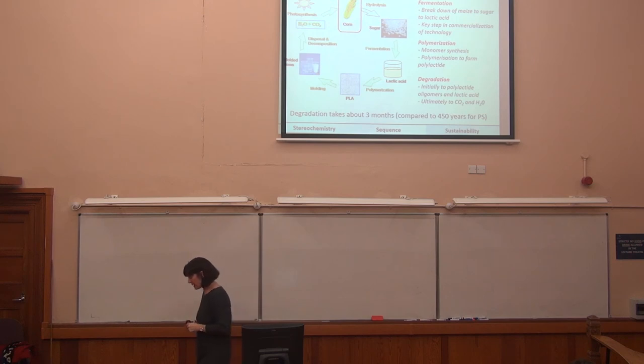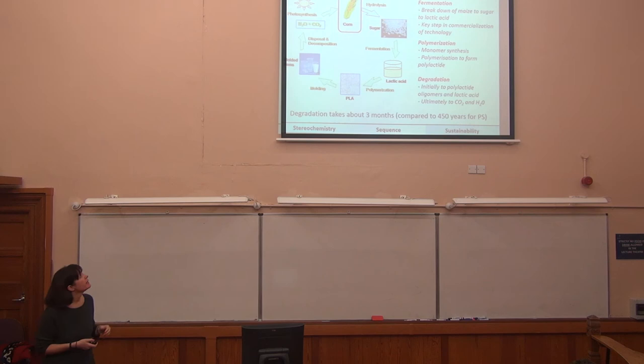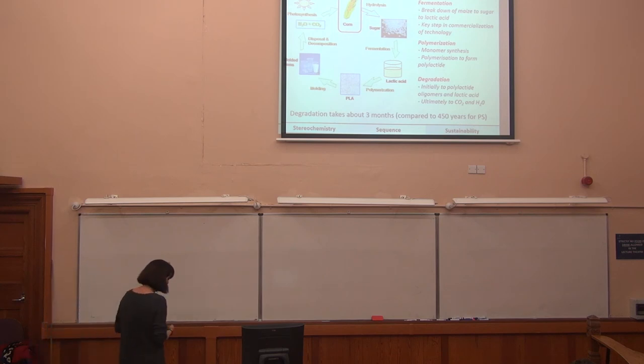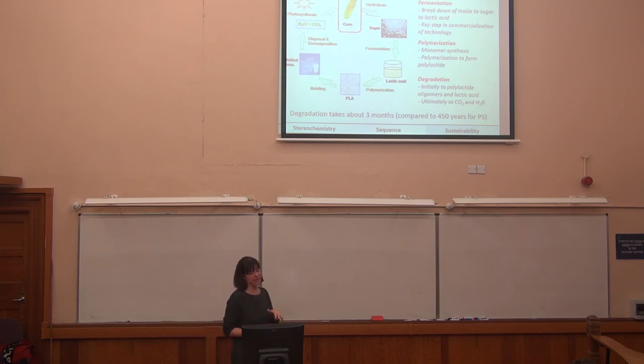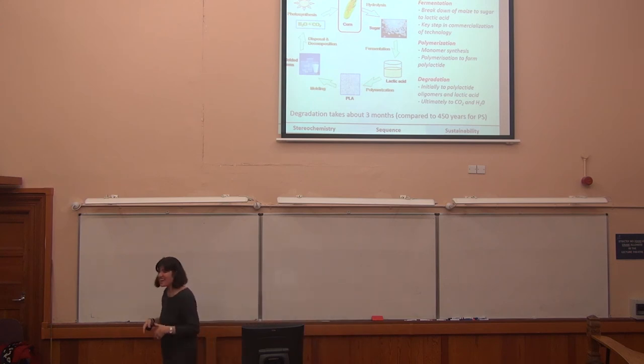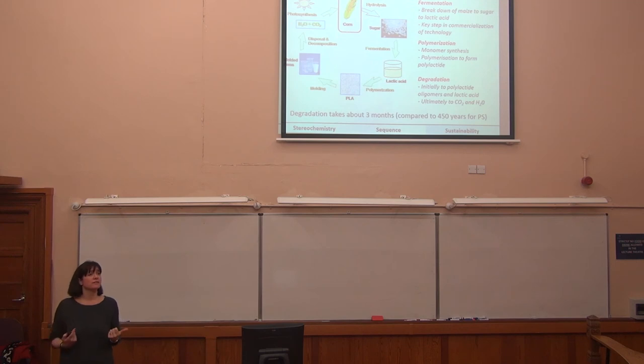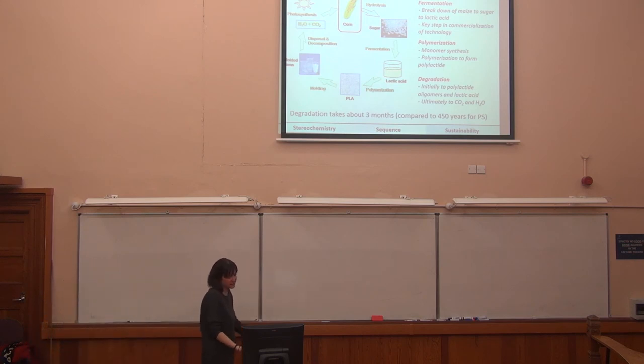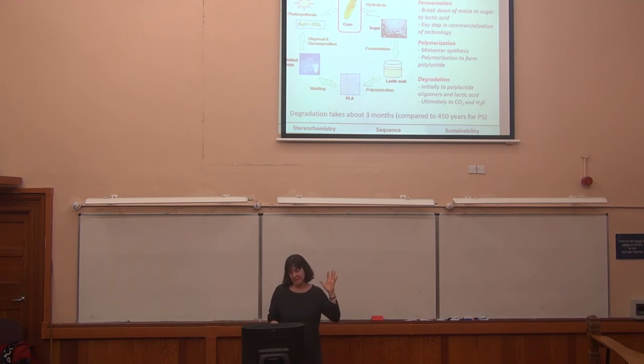And we do a lot of work with polylactide, and I told you a little bit about it earlier, but we do a lot of work because we're quite interested because it can be produced from corn, and this lactide cycle is actually very efficient, and degradation of a polylactide ball takes about 3 months compared to 450 years for polystyrene. And as I said, if you use stereocomplex polylactide, the material properties are actually not dissimilar from polystyrene. Yeah, so it's a potential replacement. It's still at the minute too expensive. NatureWorks in the US are trying to push it forward a little bit to try and increase uptake. Who knows? But yeah, this is a good example.